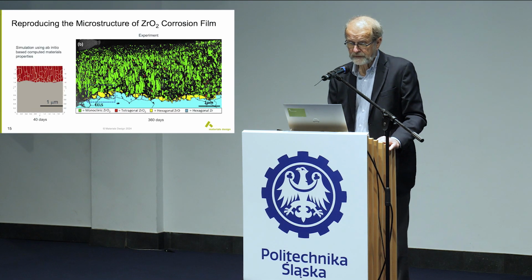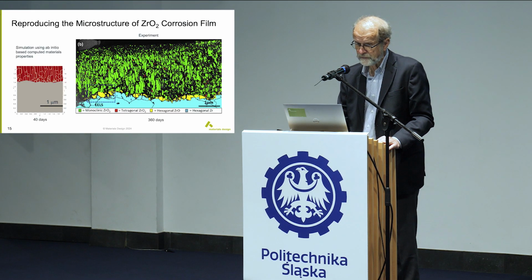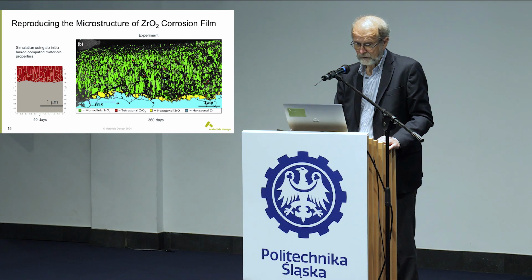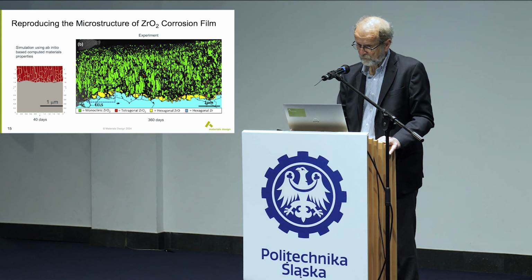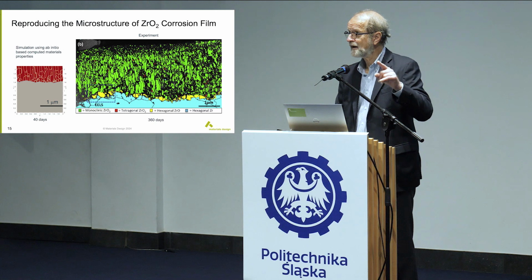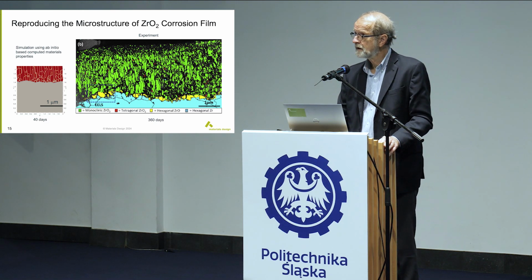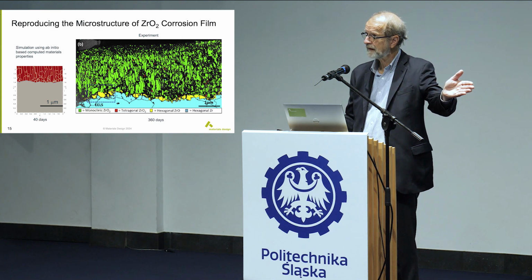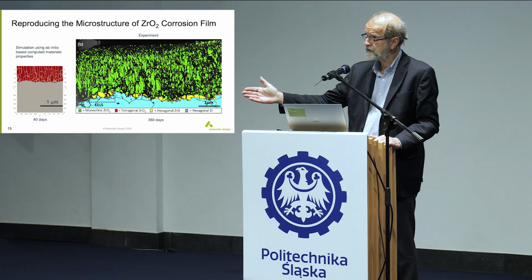So let's compare this result from our simulations with experiment. This is again the TEM image. Look at the size, 1 micrometer, 1 micrometer. I would say that's a remarkable agreement in the overall morphology, also in the fact that we're getting an interface that's warped. And this is after 40 days. That's not computing time, that's the time that we're simulating. So we have come from the nanoscale, from the atomistic level, all the way to the microstructure level.